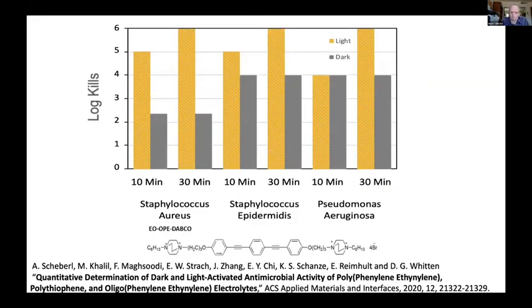Now, in the last year or so, we've really focused on how fast these react and how complete the killing is. Are they really going to be able to disinfect the surface or not? So we've been looking at their reactivity. We did a series of tests on Staph aureus, Staph epidermidis, and Pseudomonas aeruginosa. We use lab strains, but all of these occur as strongly infecting agents. We had been doing tests around 30 minutes, and we thought that was long enough to give us some reactivity.